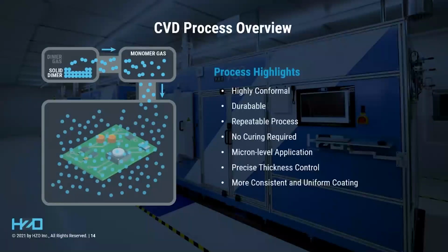It takes anywhere from 5 to 20 hours from door shut to door open, depending on the outgassing of the boards and how thick your coating needs to be. Most chambers are cylindrical. HZO happens to use a large rectangular chamber for better loading efficiency for our Parylene processes.